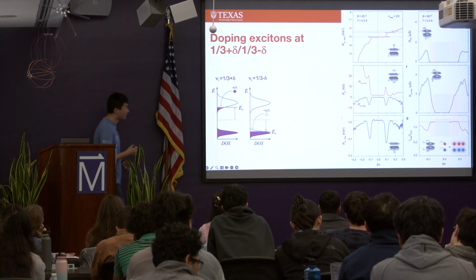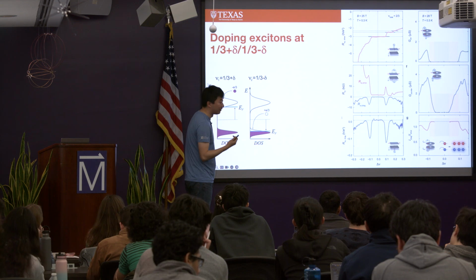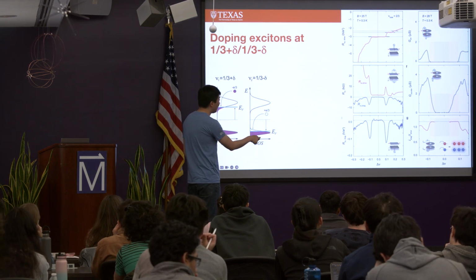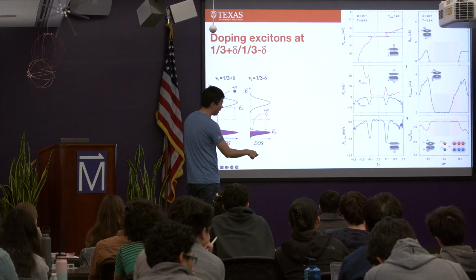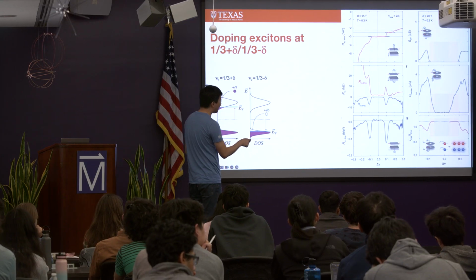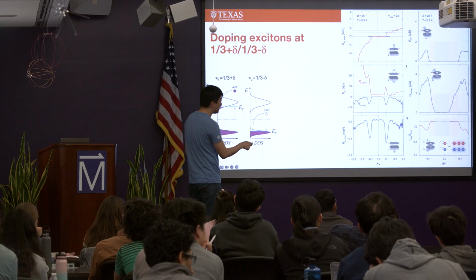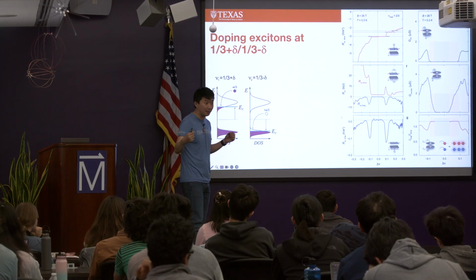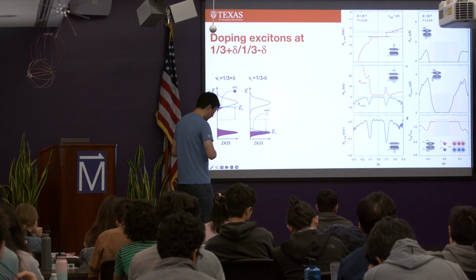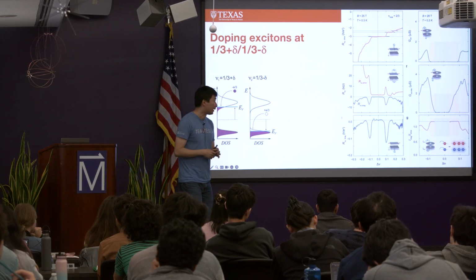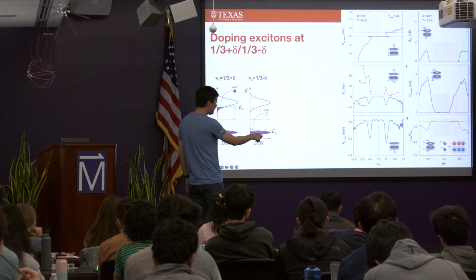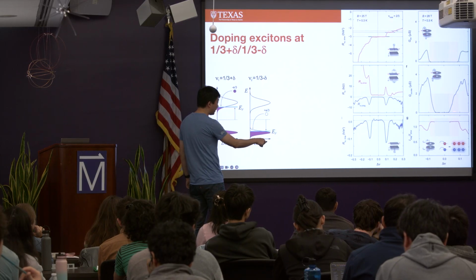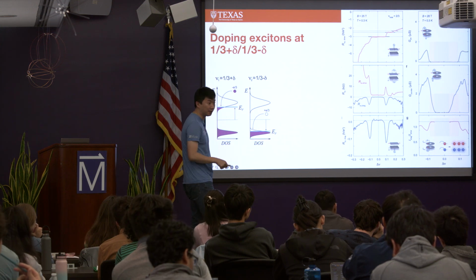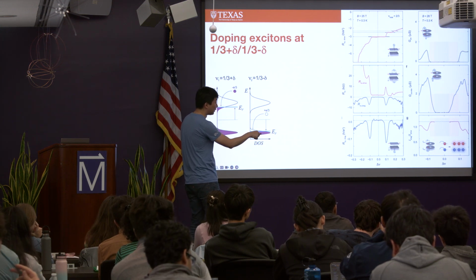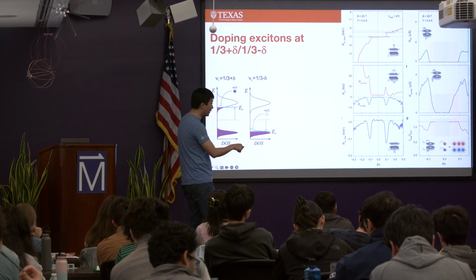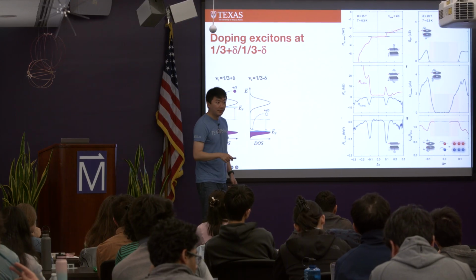The Corbino data is a lot more definitive and indicative, right? So again, we're just changing layer imbalance at total filling of 2/3, right? The top panel is plotting parallel flow conductance that shows a very large range of insulating state, meaning that over this entire range, there's a very robust charge gap, right? But if you were to measure counterflow measurement, right, at the two ends of this range, the counterflow conductance is non-zero, while the parallel flow conductance is still zero, right? This shaded red region. And over this region, you can see a perfect drag response, right?